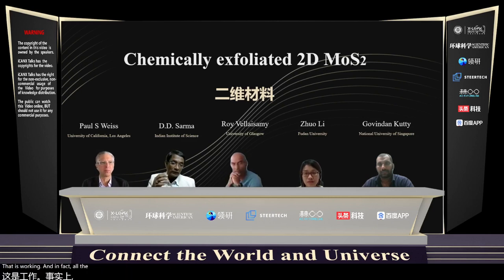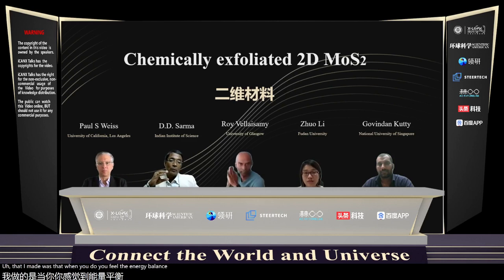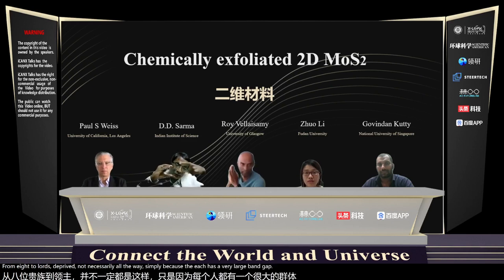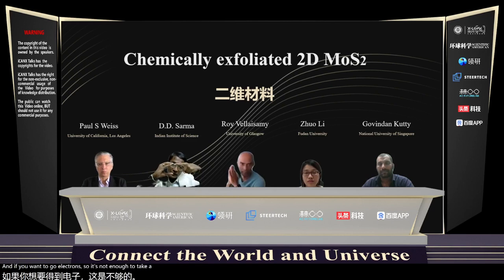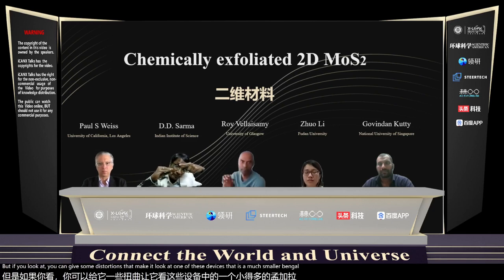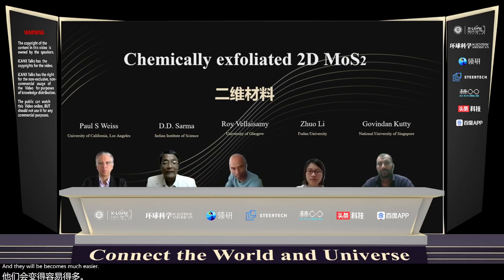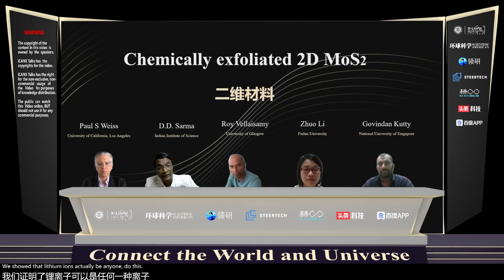In fact, one rather speculative statement that I made was that when you dope, you tilt the energy balance from H towards T prime, not necessarily all the way, simply because H has a very large band gap. And if you want to dope electrons so high up, it's not energetically stable. But if you can locally give some distortions which make it look like one of these T prime phases, that has a much smaller band gap, and then doping becomes much easier. That, I suspect, is the reason why we showed that lithium ions play an important role in kinetically giving rise to more of this metastable T prime phase. It looks somewhat like pinning. Exactly, it is pinning. That's why I also kept referring to the defects.